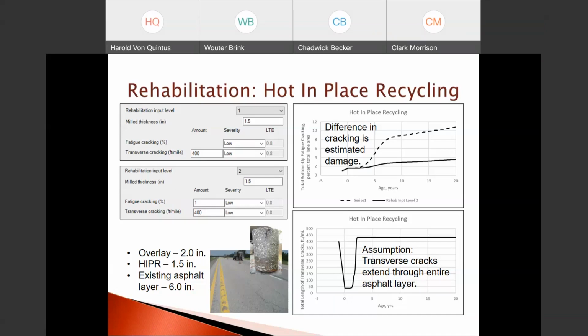So it is suggested that doing rehab input level 2 for hot in place recycling, as well as other options, for bottom up fatigue cracks, if we don't have cores to confirm whether there's bottom up or top down or FWD testing, that we just assume that any cracks in the wheel path observed is assumed to be all bottom up cracking. And that would reduce any potential discrepancies between rehab input level 2 and rehab input level 1. Would help reduce them.